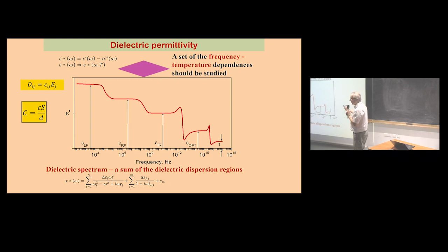The contribution can be 10, but it can also be thousands. And then in ferroelectric materials you can have a contribution from domain wall motions, or in non-homogeneous systems with non-homogeneous conductivity, you can have additional dispersion, the so-called Maxwell-Wagner relaxation, which can finally give you permittivity in the millions.